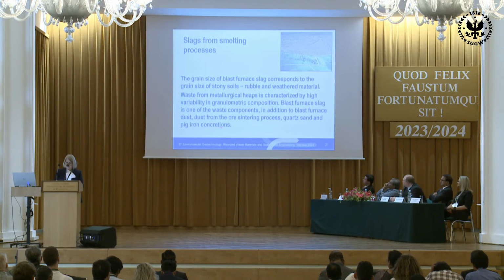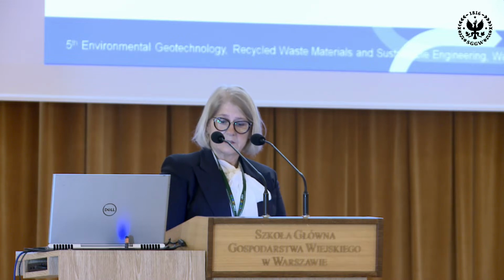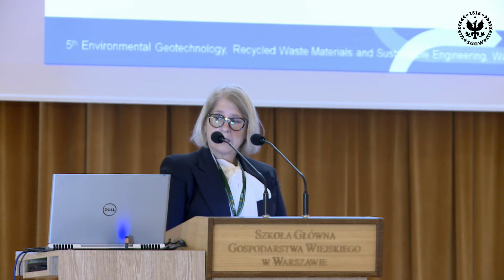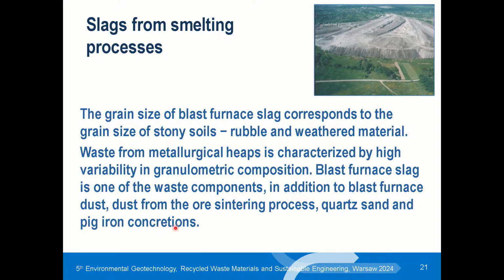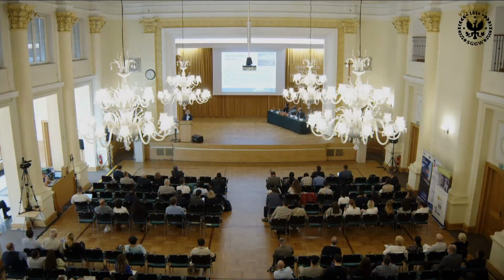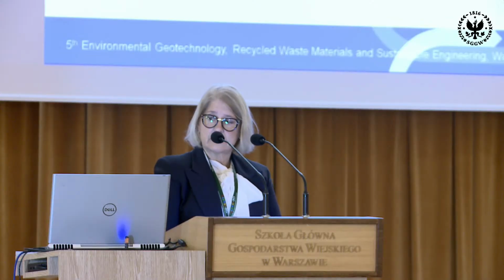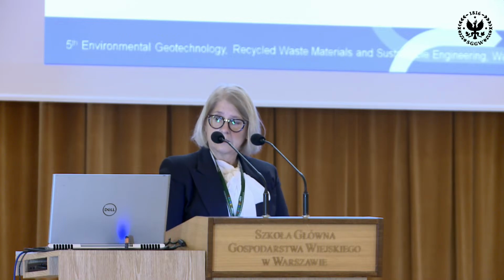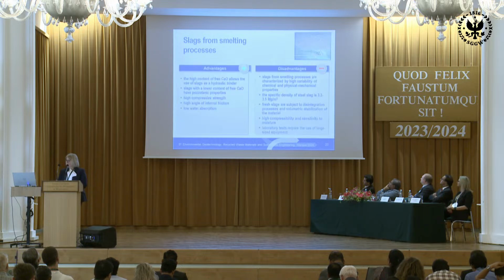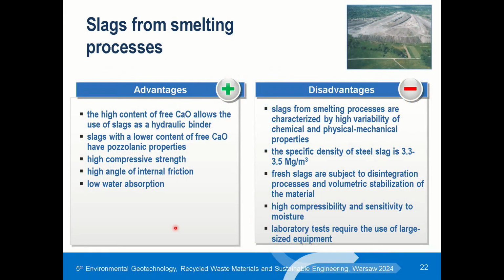The grain size of blast furnace slags corresponds to the grain size of stony soils, rubble, and weathered material. Waste from existing metallurgical heaps is characterized by high variability in granulometric composition. It depends on the type of the waste which was disposed, but nowadays this type of waste is disposed separately. Advantages are high compressive strength, high angle of internal friction, and low water absorption. Fresh slags are subject to a disintegration process and volumetric stabilization of the material, and slag has high compressibility and is sensitive to moisture.